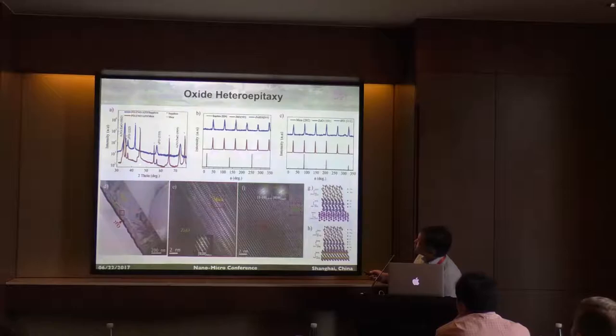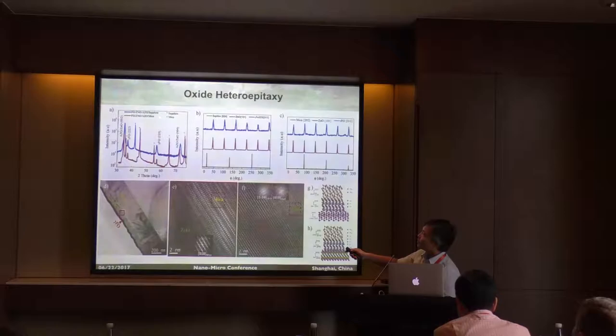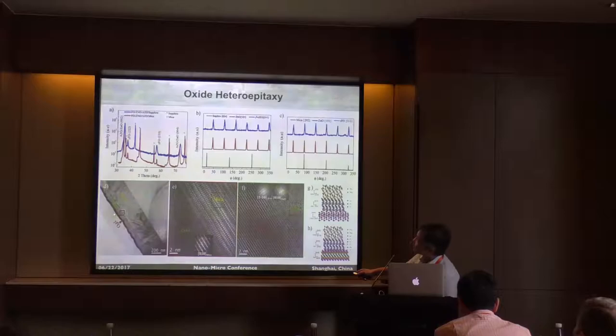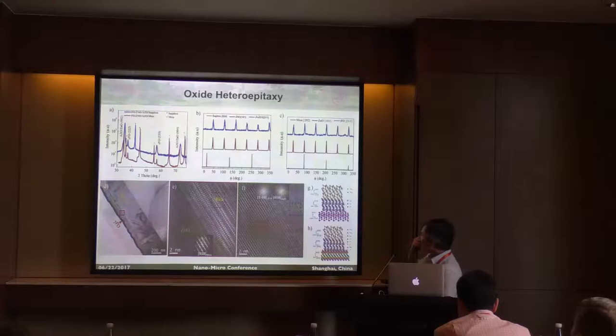Here, a single crystalline substrate is used as a reference, and we can see very nice epitaxy. We duplicate the same structure on muscovite — you can see in the TEM image: this is the muscovite substrate, here is the zinc oxide, and we have the iron oxide on top. The epitaxial relationship between iron oxide, zinc oxide, and the muscovite substrate can be determined — they have a well-defined orientation-dependent relationship.